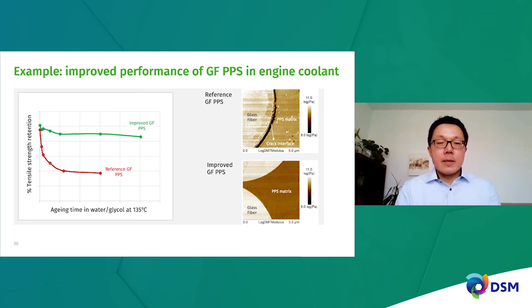So at DSM, we make a lot of improvements for our glass fiber reinforced PPS. In this case, the left-hand side figure shows you the tensile strength retention of reference glass-filled PPS versus improved glass-filled PPS as a function of aging time in water glycol at 135 C. So we make an improvement at the interface such that the retention is now going from the red curve into the green curve, so pretty stable.